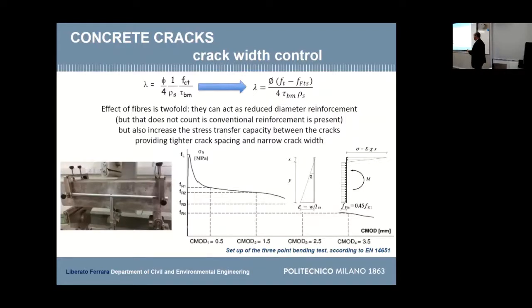We have now in the codes, in the standards, the tools to identify the properties of fiber reinforced concrete. This is a 3-point bending test on a notched prism. You make the test, you record the results, you plot the results in terms of nominal stress. Just keep in mind, this is not a true stress. First of all, because the test is a bending test and is not a tensile test. But also because we calculate the stress from the load. We never measure a stress, we measure a load. And from the load, we calculate the stress using the De Saint-Venant solid formula. De Saint-Venant assumption is linear, elastic, homogeneous, isotropic. Concrete is not even that. So this is just a way in which we convert the load into stresses, so it's nominal.